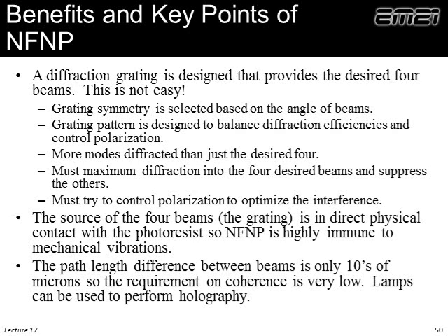So the light does not have to be that coherent. In fact, what I've shown in my research is that we can produce very usable interference just with a lamp, which is crazy, that we could even think of doing holography or anything holographic with a lamp. But that's just because the beams don't separate that far. The light does not have to be that coherent.